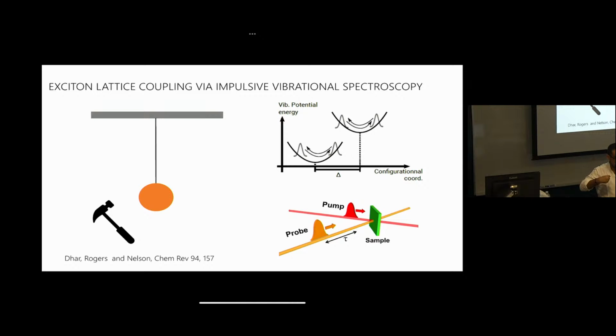These are coupled to phonons. All the lattice starts ringing with the phase that you impose with your femtosecond pulse. And so all of these oscillators are in phase. You essentially form these vibrational wave packets that are oscillating in the ground state, and your time-dependent transition probability will be modulated by this vibrational wave packet oscillating in the ground state. So what you get are